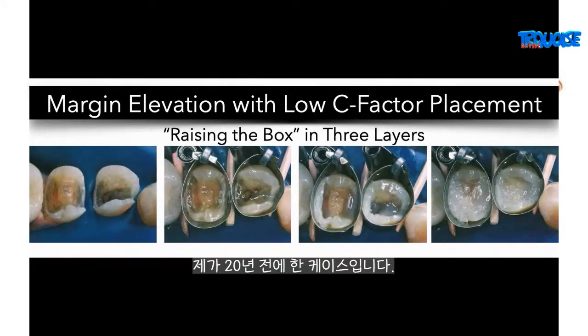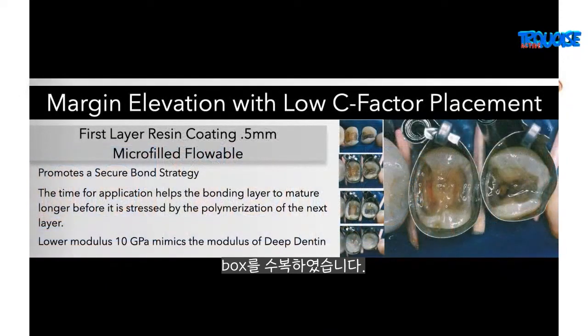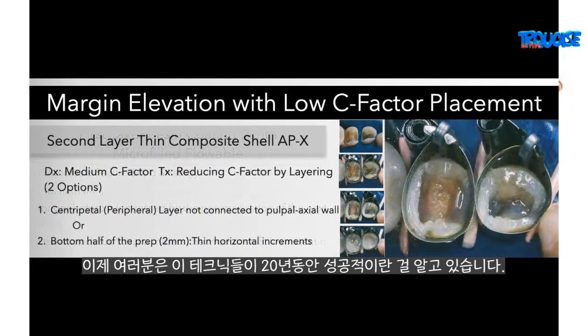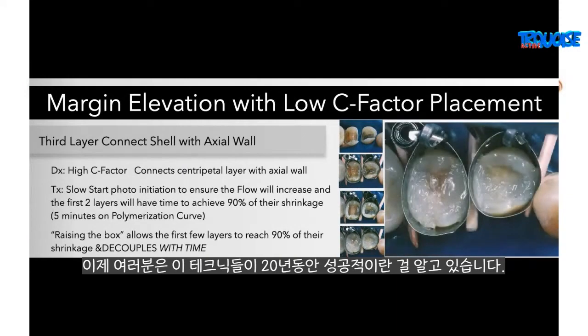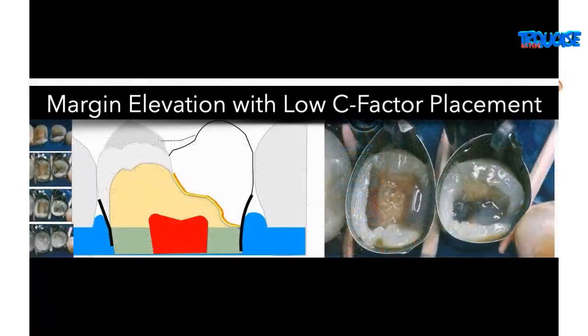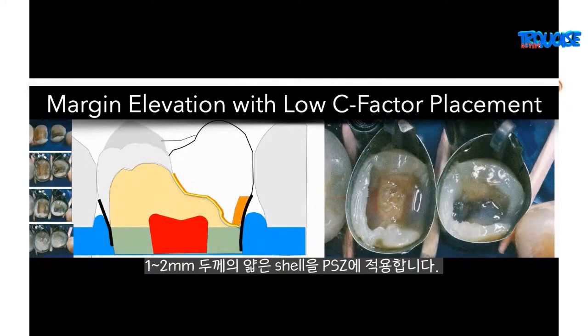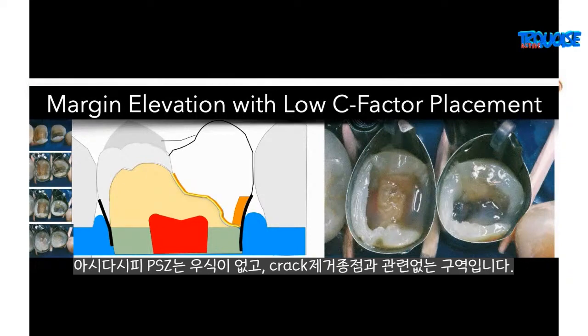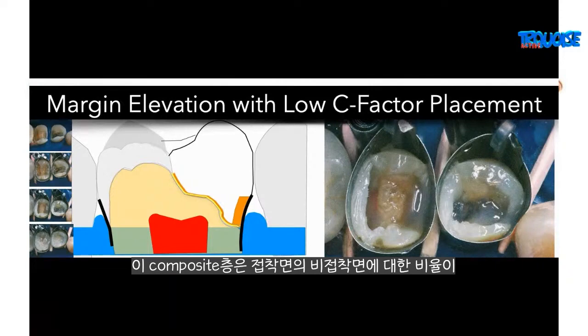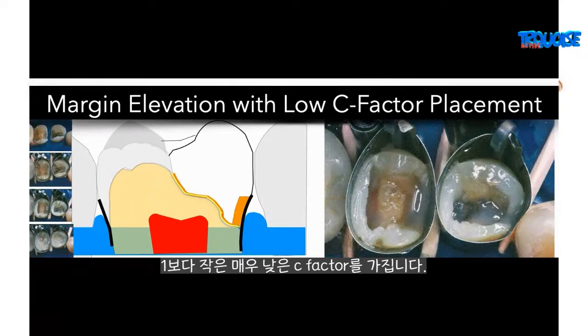We just need to read it and implement it and be guided by mentors who have been doing it. Here's a case that I did 20 years ago using these low C factor preparation and incremental filling techniques. And as these boxes have been restored, we have now 20 years of success with these techniques. So we do our immediate dentin sealing, our resin coating, and then we do a thin shell. And that thin shell would be 1 to 2 millimeters. And that would be on the peripheral seal zone, which is the caries-free and crack removal endpoint-free area. And that layer of composite has a ratio of bonded to unbonded surfaces that is a low C factor, less than 1.